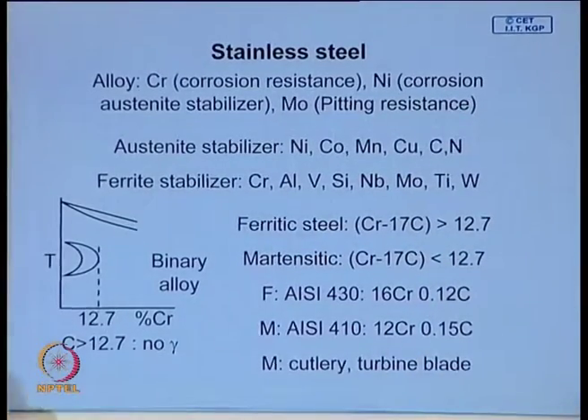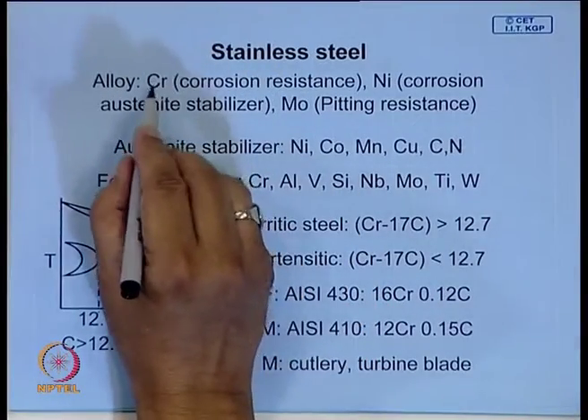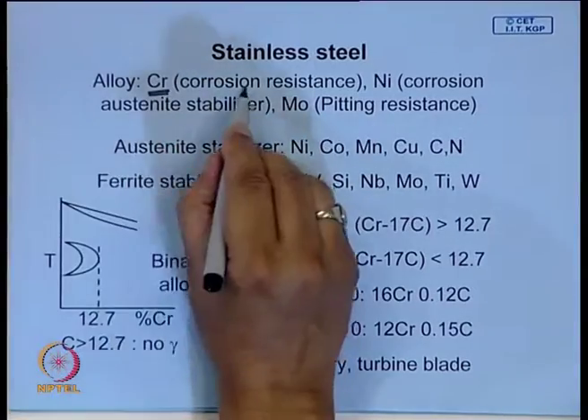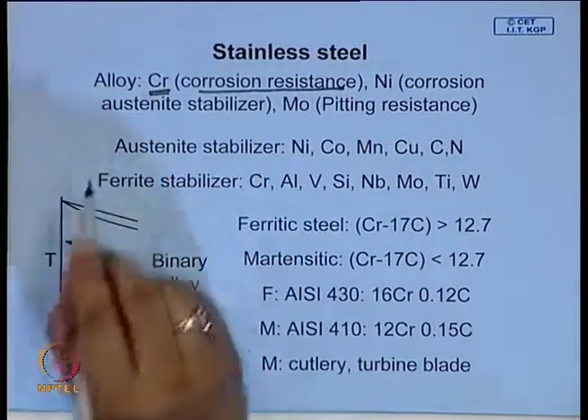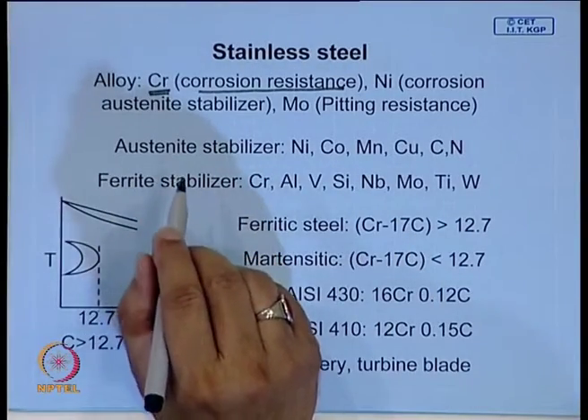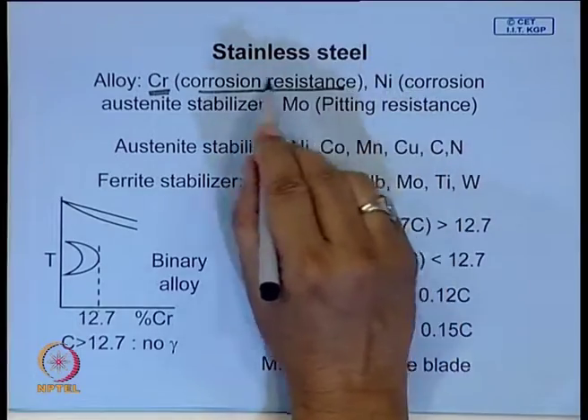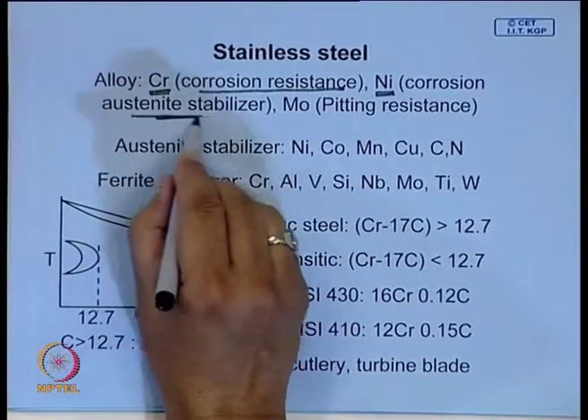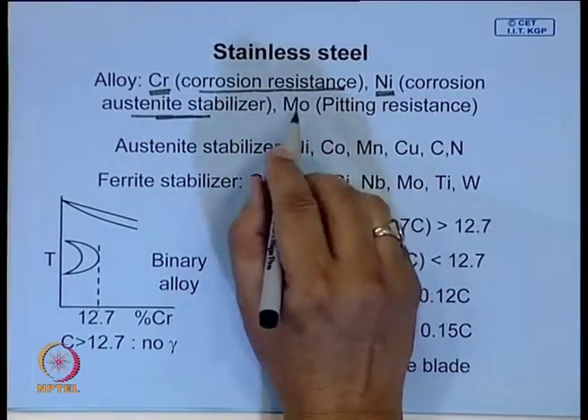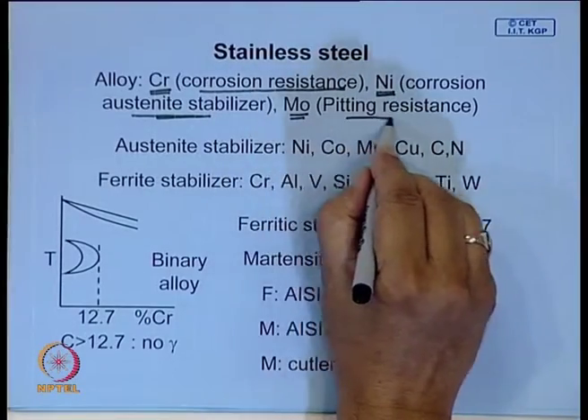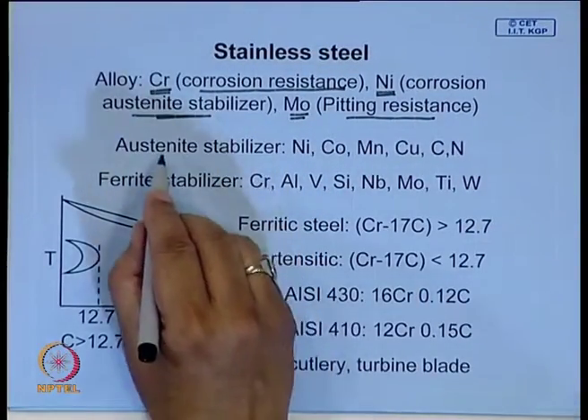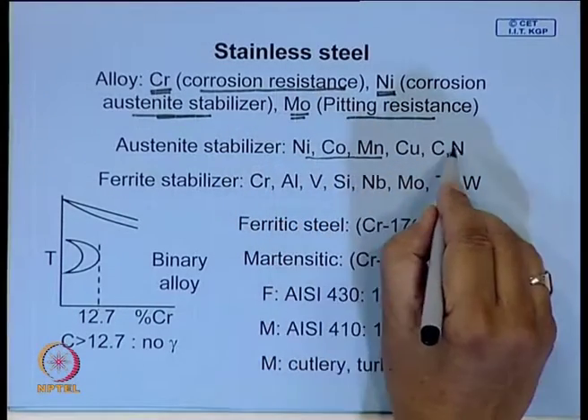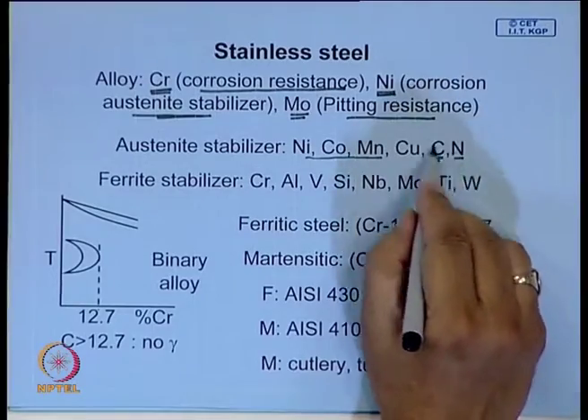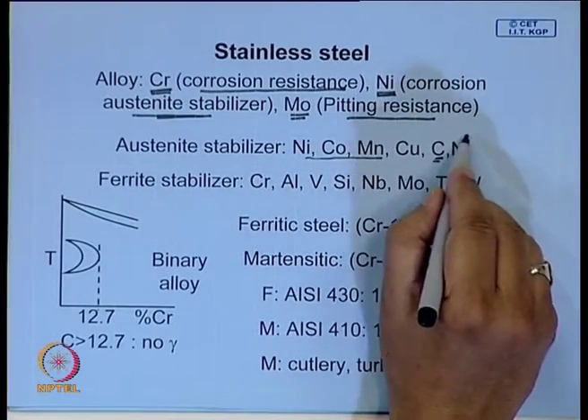Now, let us talk a bit on stainless steel. We have seen the main alloy element which gives stainless steel is chromium. You must have at least 12% chromium to form a protective coating of chromium oxide. Along with that, we also add nickel to improve corrosion resistance. It also is an austenite stabilizer. We will see that if you add a certain amount of nickel, then the steel becomes austenitic, and we add moly to give it pitting resistance. Some of the common austenite stabilizers are listed here, even carbon and nitrogen are also good austenite stabilizers.